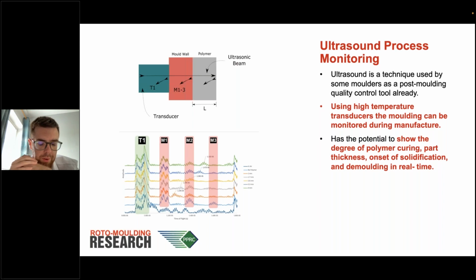So over the 4 years that I was doing my PhD, I was looking at applying an ultrasound transducer, which is this T1 signal, onto the wall of a mold, which is M1 to M3, because you get returning echoes from the sound wave that's produced from the transducer. And there's also an element of the sound that passes through the polymer and reflects back again.